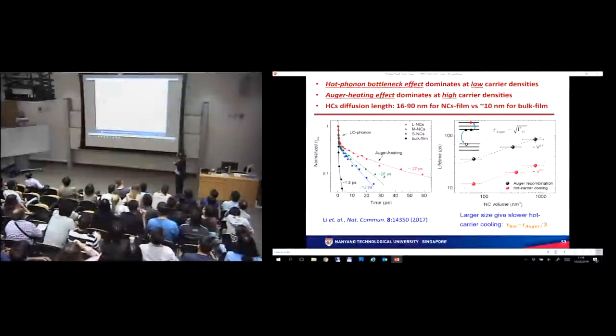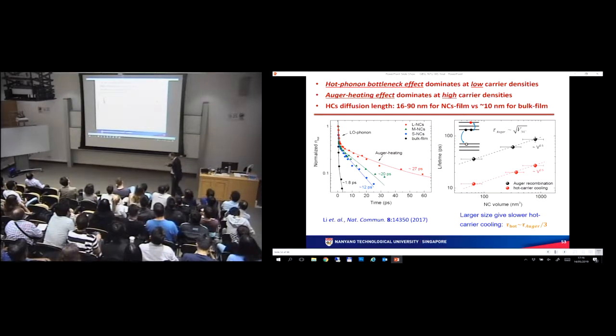Now, I will very quickly talk about the mechanism, because the mechanism was also changed. We have a separate team, which I'll show in the next couple of slides, on a more detailed study on this. In this case, there are 2 mechanisms at work. One is the hot phonon bottleneck effect, which dominates at low carrier densities. At higher carrier densities, you have an Auger reheating process. I'll talk more about these mechanisms in the next couple of slides.